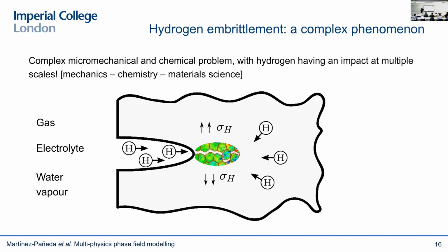We know the basics. We know that hydrogen coming from any hydrogen containing environment, could be hydrogen gas or electrolyte or water vapor, will enter the metal. It will diffuse through the crystal lattice and it will be attracted to areas of high hydrostatic stress or high volumetric strains, where there is space in the lattice for the hydrogen to accumulate. But then hydrogen interacts in this fracture process with the metal in multiple ways and at multiple scales, changing the dislocation mobility, changing the bonding strength of the metal atoms. So the physical picture is complicated.